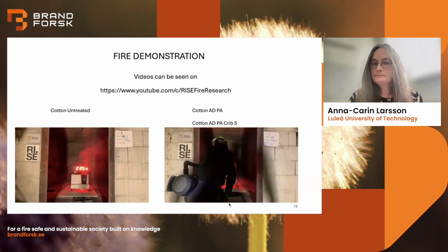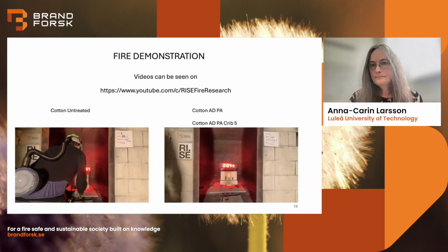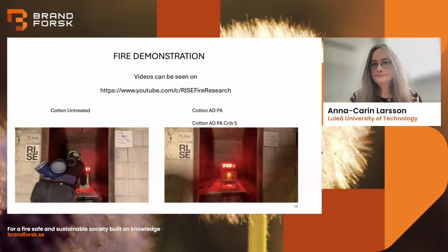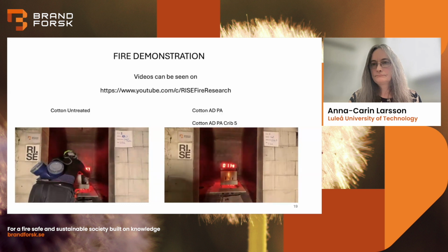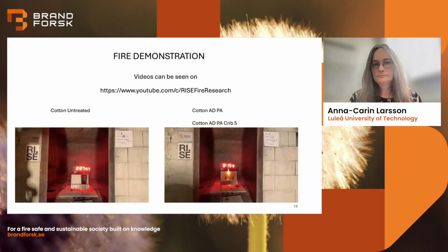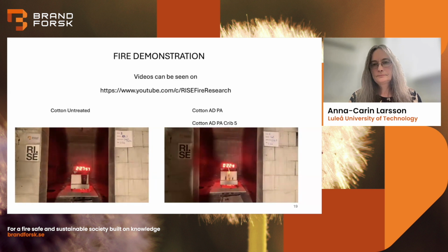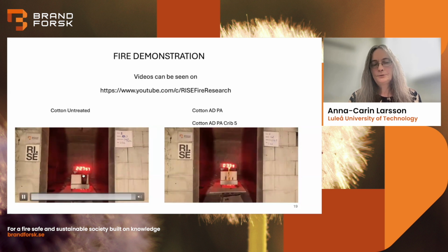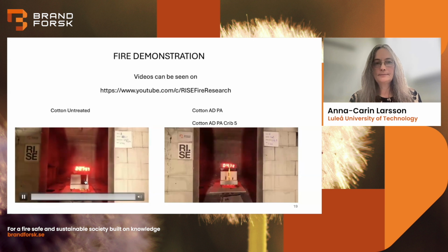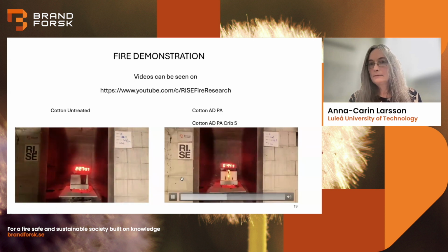So it's crib 5. After 2 minutes, 15 seconds, the fire was extinguished and the experiment stopped for this untreated material. For crib 5, the fire is supposed to continue for 10 minutes before the experiment is stopped.